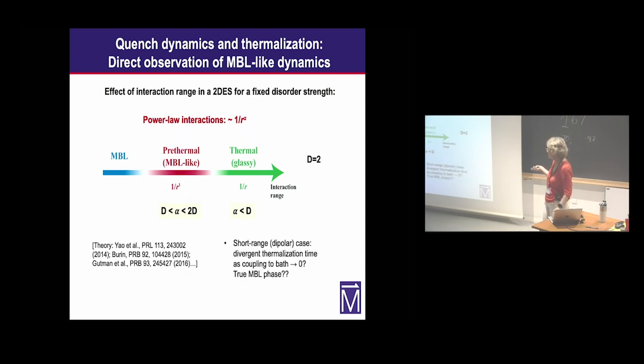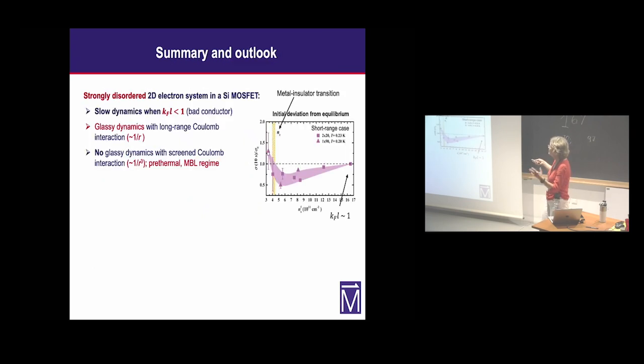Now, again, we do have some finite coupling to a bath, and the dependence is very strong. If we could make it go to zero, we could speculate that maybe we would be in a true MBL phase, but I think we'll never know. Anyway, the conclusion is that when k_F l is less than 1, when the disorder becomes important in these strongly disordered 2D systems, you see slow dynamics. Glassiness is observed when the Coulomb interaction is 1/r. And importantly, glassiness does not survive when the interaction is screened. This was our original motivating question for these studies. But instead, we see MBL in sufficiently isolated systems.